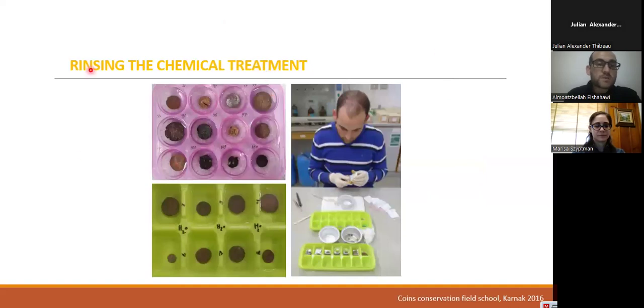Here's the rinsing process using distilled water, and at minimum we do this 3 times, each time for 1 hour, and then you have to check your pH. If your pH reaches neutral again, which is 7, that means two things. You have completely gotten rid of all the corrosion layers from the coins. Also, there are no residues of the chemical materials that you used in the chemical process.